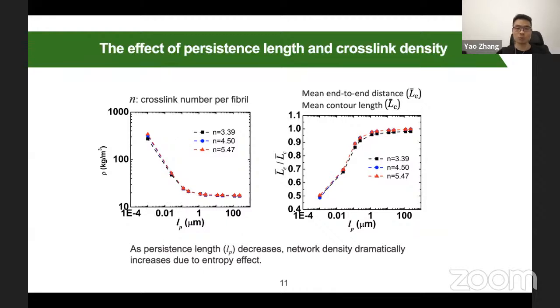Now we try to tune the structure of this network. We have two methods. One, we can control the persistence length of the fiber. The second one, we can control the crosslink density of the network. Here, we use N to indicate the crosslink number per fiber, and LP is the persistence length of the fiber. So we first check how the persistence length and the crosslink density affect the density of the network. Here you can see the left figure shows the density rho of the network as a function of the persistence length of the fiber. No matter how you change the crosslink number N, as long as your fiber persistence length increases, the mass density just decreases.